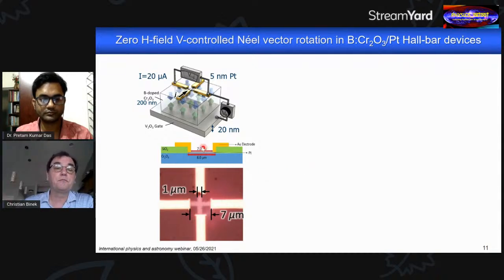Here you see a cross-section, and here you see the optical image of the lithography we did in our Nebraska Center for Materials and Nanoscience. Here again, the same device. And now the results. In particular, I'd like to stress the one above here, which is taken at zero applied magnetic field. No field whatsoever. Only electric fields are applied here across the boron-doped chromia.